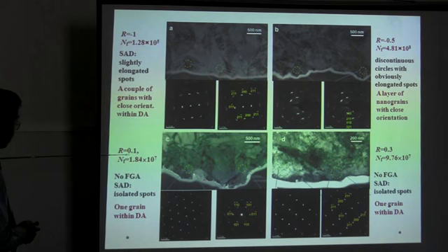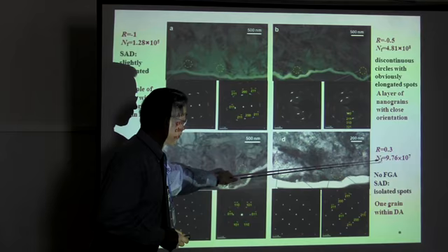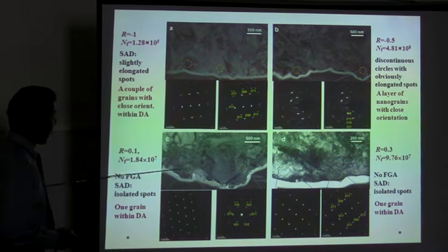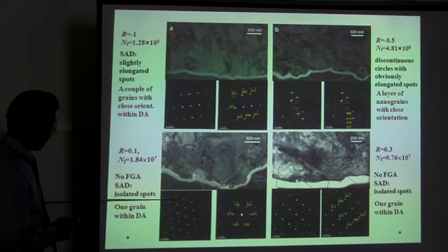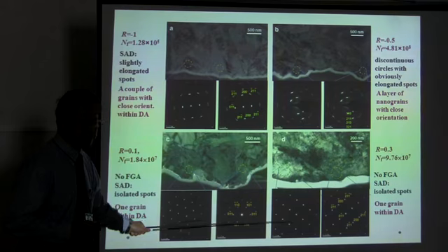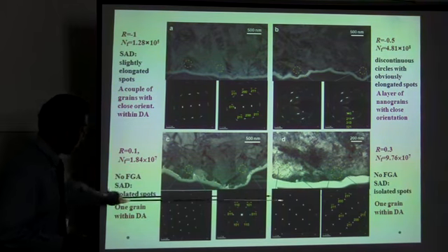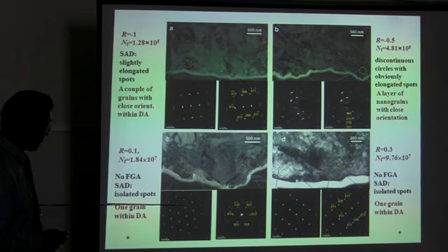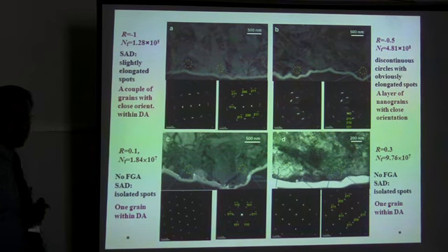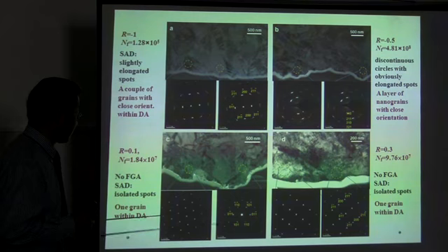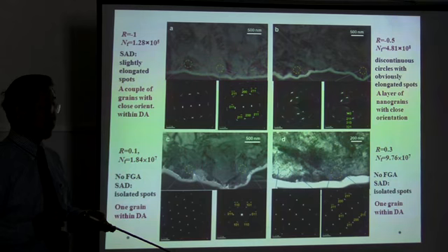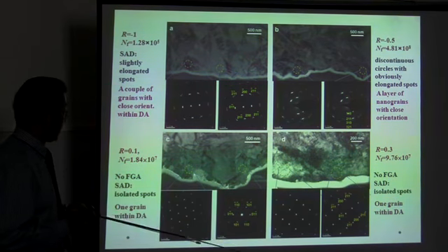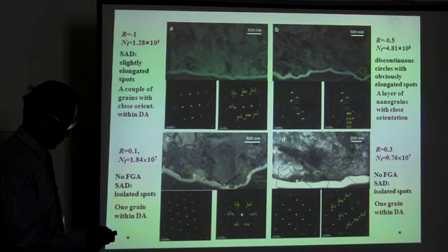But for the stress ratio of plus 0.1 and plus 0.3, underneath the fracture, the crack initiation area, there are all isolated spots, showing just a single grain there. So this answers our two predictions.